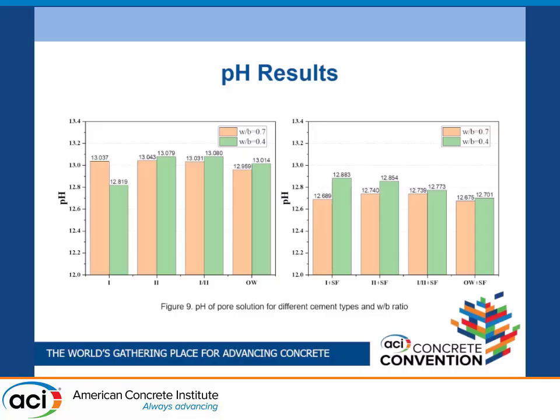And when we use silica fume, the pH is significantly reduced, and this has two things to do with it. One is the use of silica fume reduces the cement content, that's why the pH decreases. And another is silica fume is pozzolanic and consumes calcium hydroxide, so the pH is reduced.